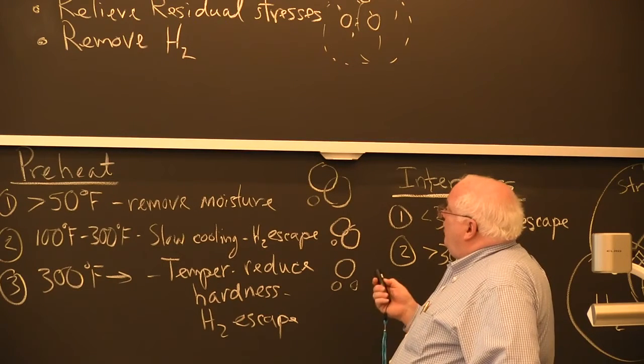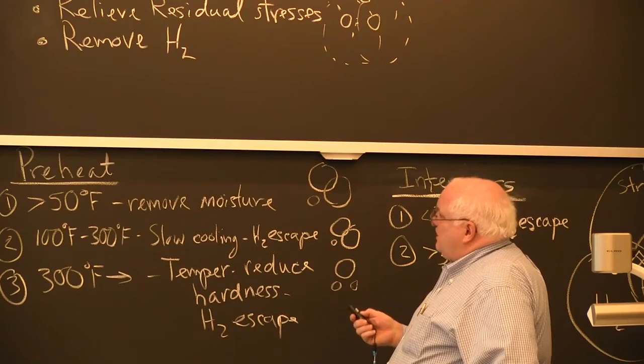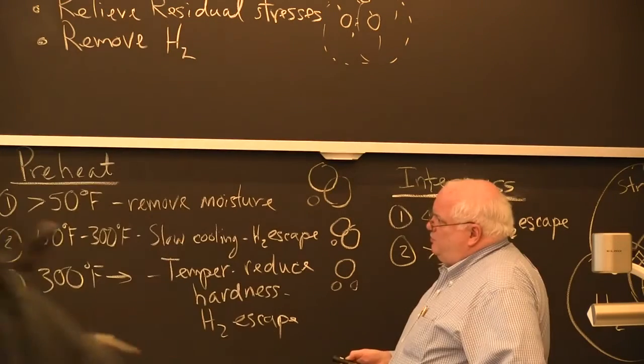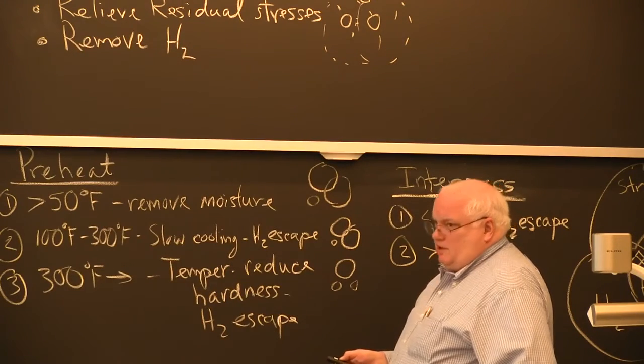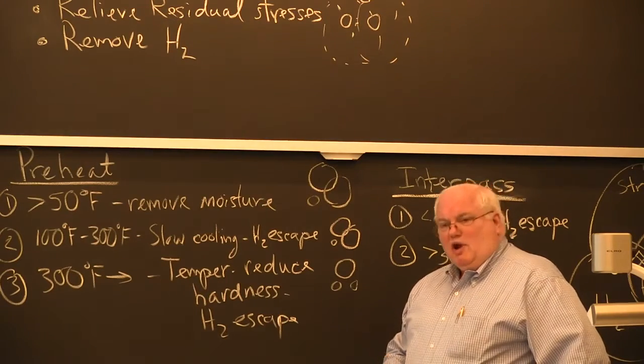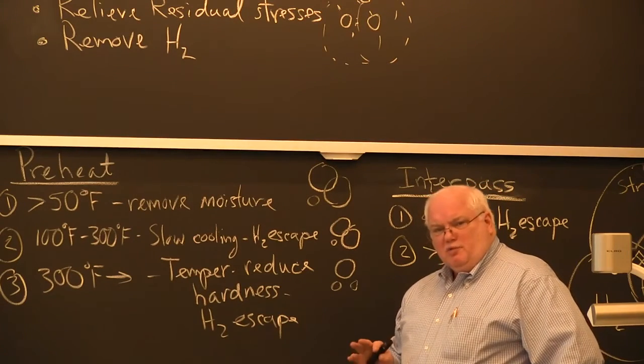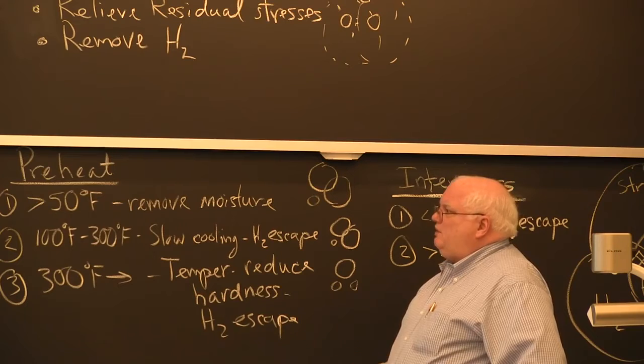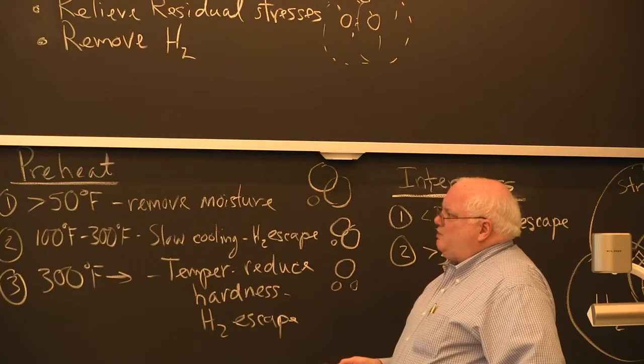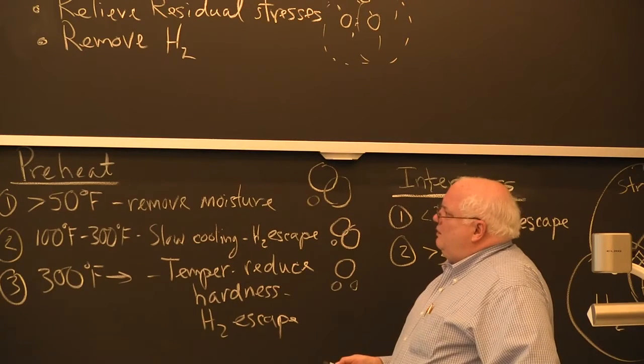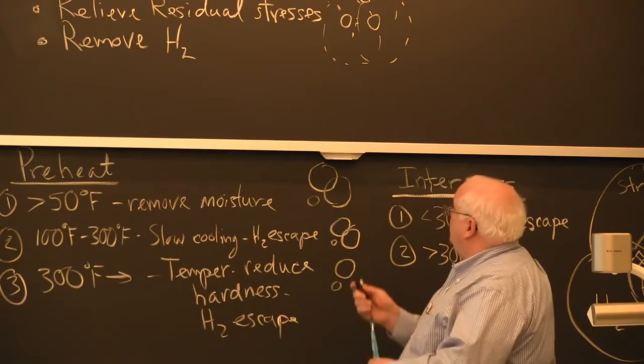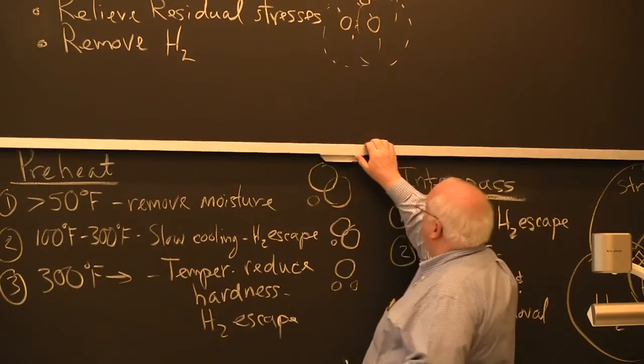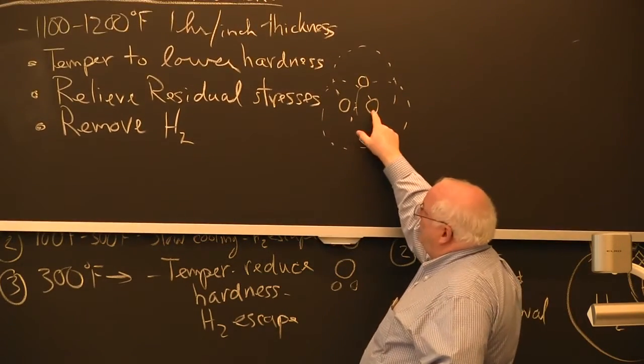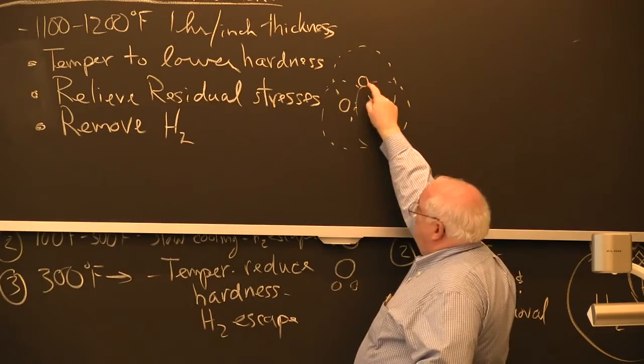You temper to lower the hardness. What this does at this temperature, you're tempering to lower the hardness, which means I'm really lowering the hardness. I mean, you're not losing the martensitic structure, but you're getting to be relatively soft compared to the maximum hardness. And that's going to be good in terms of lowering the hardness circle, okay? You're also relieving the residual stresses.